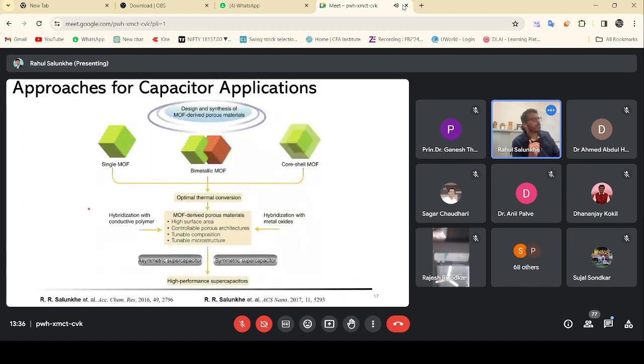So we don't skip this one. There are various approaches for the capacitor application. In our work, we have developed various types of approaches for capacitor applications. We have used single MOF, bimetallic MOF, core-shell MOFs, and optimal thermal treatment that leads us to achieve various MOF-derived porous carbon materials. They have a very high surface area, controllable porous architecture, tunable composition and tunable microstructure.